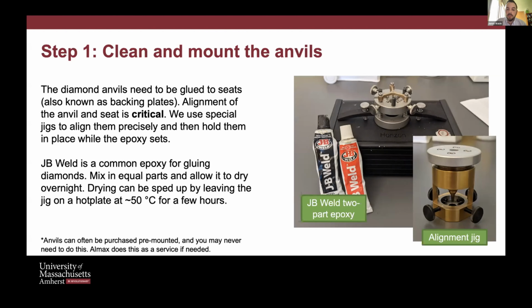And so how do you glue? We use JB Weld. I think for most groups, it would have to be a special case why you would not want to just use JB Weld. The two-part epoxy, you mix it up, you know, add it around the diamond, that will dry usually over a day. You can speed it up by putting it on a hot plate if you're in a pinch, but usually leave it for a day and it will dry, and then you've got your anvil and seats together.